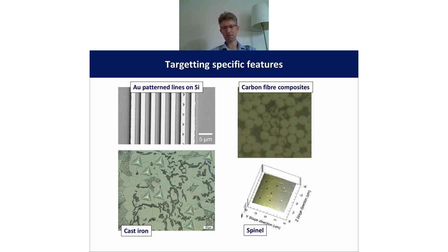On the right, again from an aerospace application, we can position indentations in the middle of carbon fibers. This one here is for the automotive industry, and this was part of a study illustrating you can put big indentations to understand these big phases, and then combine that with much smaller grid indentations to look at the mechanical properties of these smaller phases. And this one is a biomedical alloy, again where you can position automatically and get different phases in the spinel.